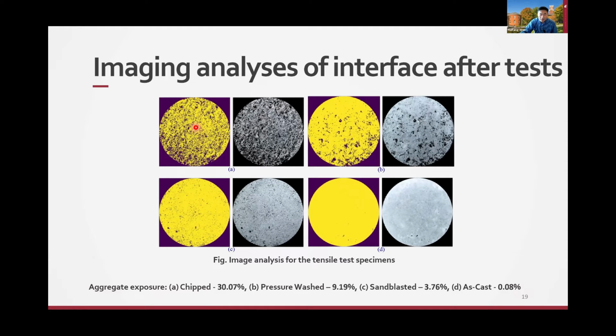If it's adhesive failure, which happens at the aggregate and the paste, you will see more aggregate or rocks exposed. Based on the imaging method, the chipped method has the most aggregate exposed, followed by the pressure washing method, and then sandblasting and as cast, which has the least aggregate exposure. That also explains why, after the tensile test, the chipped method gives you the highest tensile, followed by pressure washing, sandblasting, and do nothing. So that's the adhesive failure and the cohesive failure.